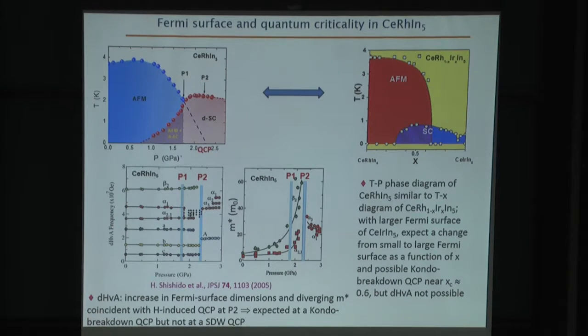So de Haas-van Alphen measurements have been made as a function of pressure, and results of those experiments are summarized in this plot of de Haas-van Alphen frequencies as a function of pressure, as well as in this plot of the effective mass of quasi-particles as a function of pressure. And what we see are two things. The first is that the effective mass of these quasi-particles diverges on approaching this pressure P2. That's expected at any sort of quantum phase transition.